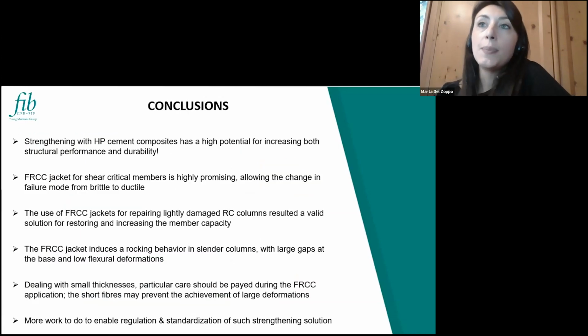So just to conclude, we have seen that the strengthening with high-performance cement composite has a high potential for increasing the structural performance and also the durability of our existing assets. So they can be used not only for surface repairing, but also for structural purposes. The adoption of such a strengthening solution for shear critical members is highly promising because it allows the change in failure mode. So with just the replacing of the concrete with a new high performance one, we can, in some cases, depending on the column, change the failure mode from brittle to ductile.